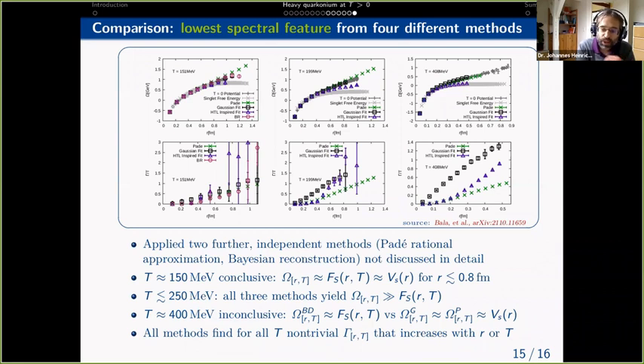And if we switch away from this HTL-inspired analysis and use another fitting model, but expand around the midpoint in the Euclidean time direction, we get more or less the same answer for the real part and for the imaginary part. So it's not yet completely clear what the lattice says, whether the potential is screened or not, but it definitely has a non-vanishing imaginary part.